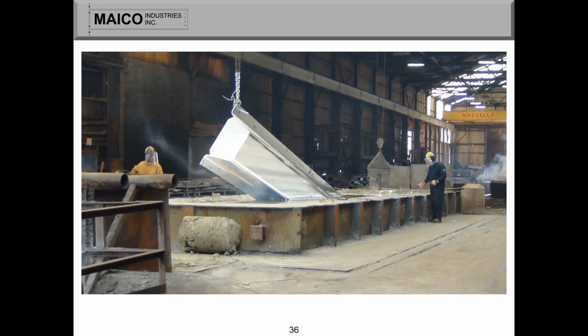This is a good picture of one of the tub girders that's in process, just coming out of the galvanizing tank. And I should mention this is a hot dip galvanizing process, whereas the material goes through a series of vats called the pickling process. And the parent material, in this case the tub girders, are immersed in cleaning solutions, acid, rinse tanks, flux tanks, prior to being fully immersed in the zinc kettle, in which the molten zinc is approximately 850 degrees. The size of the kettle there in Tulsa to allow this to be fully immersed is 5 foot 3 inches deep, 7 feet wide, and 56 feet long. So depending on the material thickness involved in hot dip galvanizing to get the cathodic protection, these pieces will stay fully immersed for a certain period of time, whether it be a minute or a couple minutes, just depends on a couple of variables.